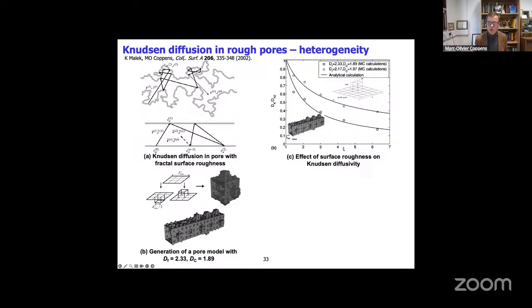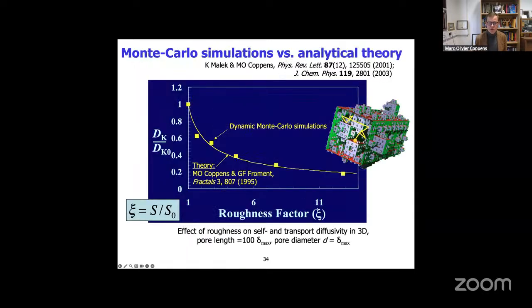And we got pretty good agreement between the kinetic Monte Carlo simulations and the experiments. And as you see, indeed, the Knudsen diffusivity normalized towards the one with smooth walls depends significantly on roughness. You see the factor is quite significant. So this is kind of a summary of dynamic Monte Carlo simulations compared with the original theory, where you get good agreement. But then this was the beginning of this century. Now move forward to the current age.